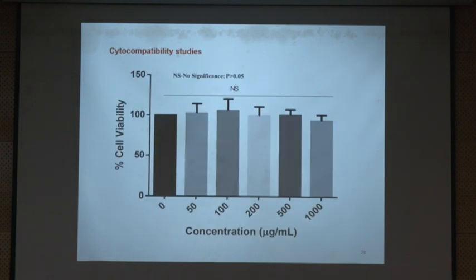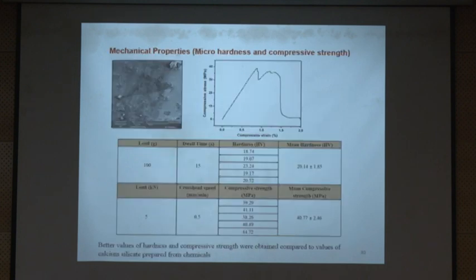And then if you see this, here the x-axis is the concentration of the material you are trying to use to check the toxicity of the material. 50 microgram to 1000 microgram per ml. I have used even 2000, 5000, even more than that. Still we are finding that our material is non-toxic in nature. See, the viability is near to 100%. So similarly, I measured the mechanical properties also, like the hardness and the compressive strength.